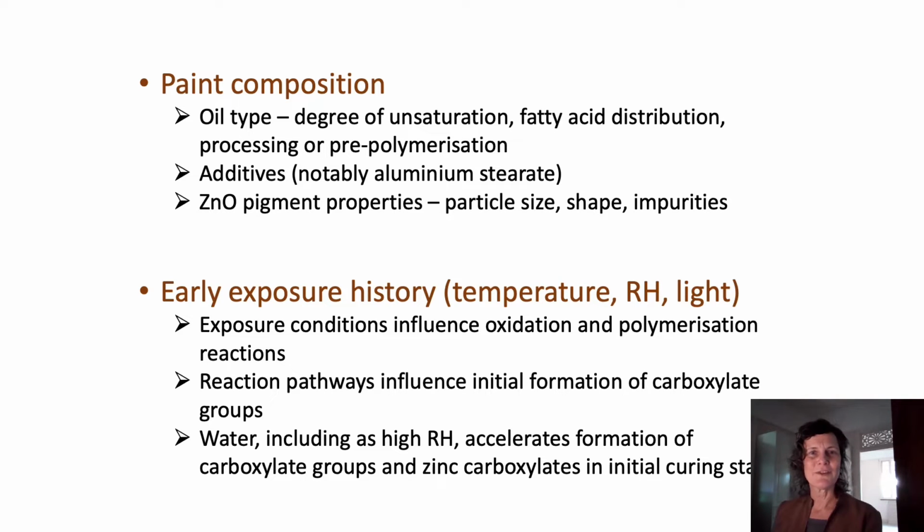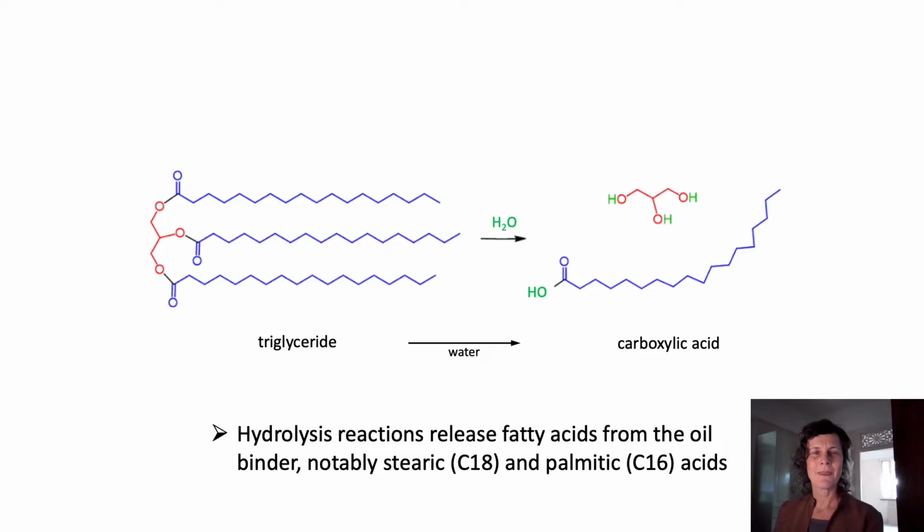There is increasing evidence too that the early environmental exposure history of a painting affects initiation and formation of carboxylate groups and consequently zinc carboxylates as the paint cures and polymerizes. Elevated relative humidity is understood to be particularly significant in accelerating formation of carboxylate groups during auto-oxidation of the oil medium. Beyond the early life of a painting,